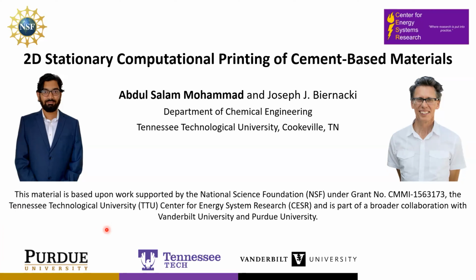Thank you, Michelle. Good morning, everyone. The objective of this study was to link relevant experimental rheological measures of printing paste to actual printing outcomes and computer-generated 2D printed constructs. Therefore, an efficient computational strategy was developed for modeling additively manufactured cement-based materials, which captures the dynamics of 2D slices at a stationary location along a print path, that is, 2D stationary computational printing.